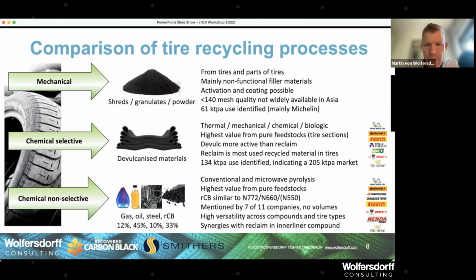There are synergies with Reclaim and in inner liner compounds. So you could put Reclaim in the inner liner, and you could also put recovered carbon black. We talk about applications a little bit later on, but inner liner is the butyl part of the tire, which is responsible for the air tightness, and recovered carbon black has a good performance in that compound.